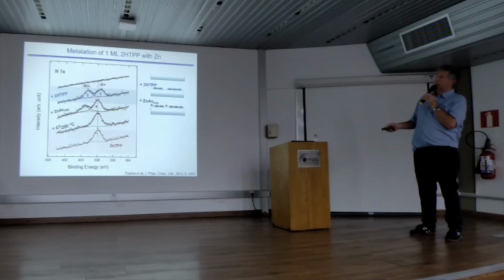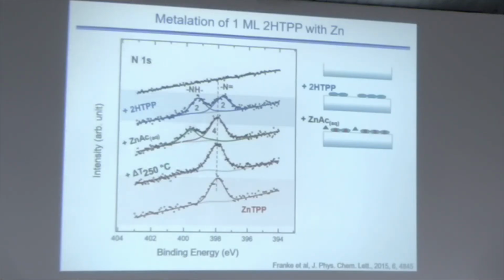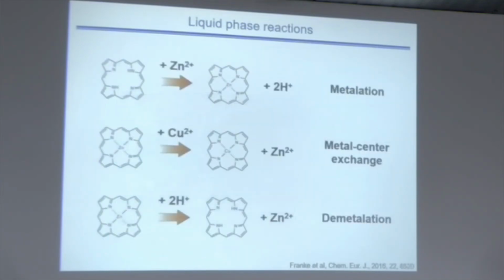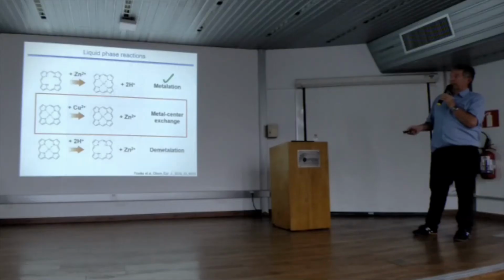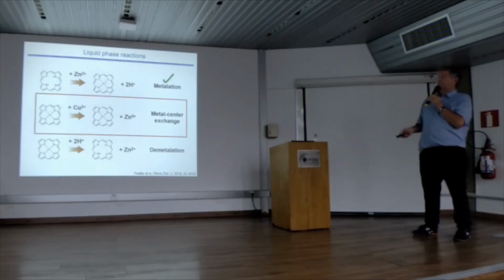Then we expose the surface to the zinc acetate in the liquid cell. We get these new and taller peaks, so this is the sum of the two. So we have a metalloporphyrin, but we have something else which we don't like. But the nice thing is, if you heat to 250 °C, what we don't like goes away. So the contamination goes away, and we have the clean zinc porphyrin. And if you compare that to a zinc porphyrin prepared in UHV, you see perfect agreement. So that works.